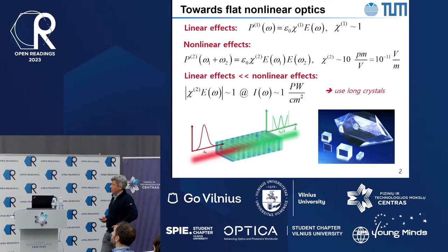Can similar elements be built for nonlinear optics? In nonlinear optics, we know that nonlinear effects, for example, sum frequency generation, the polarization for these nonlinear effects, P2 at some frequency, is proportional to the nonlinear susceptibility tensor of the medium times the square of the electric field. That's what gives the frequency mixing. And traditional materials have values of this nonlinear susceptibility of the order of 10 picometers per volt.